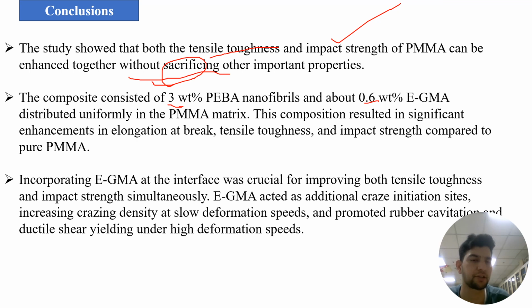Also in some other papers I see that around 3% gives good results, especially for fibers. The last point: incorporating EGMA at the interface was crucial for improving both tensile toughness and impact strength simultaneously. EGMA acts as an additional craze initiation site, increasing crazing density at slow deformation speed, and promotes rubber cavitation and ductile shear yielding under high deformation speed. So overall, the strength, tensile toughness and impact strength were improved in this paper.